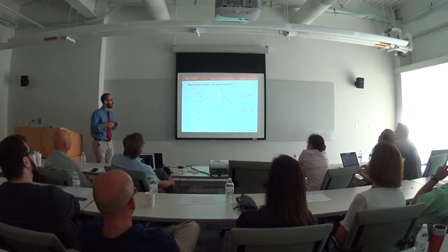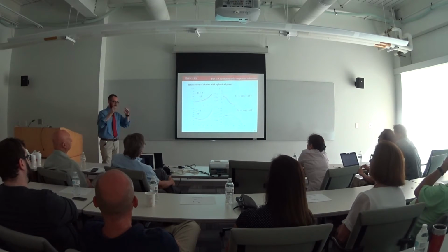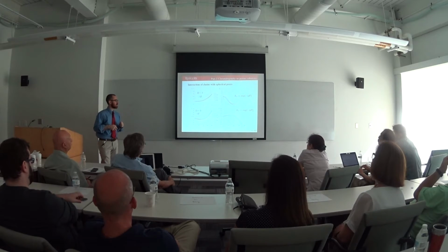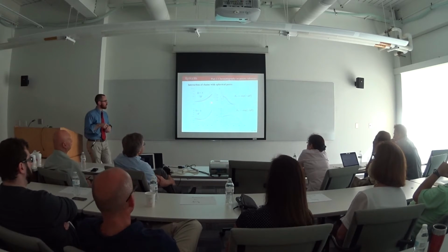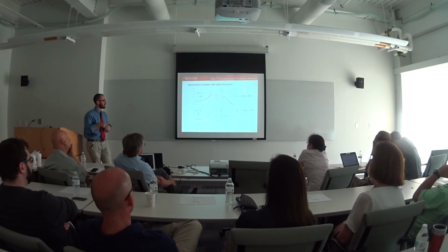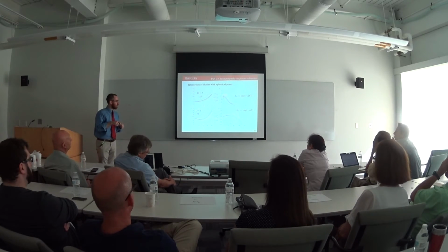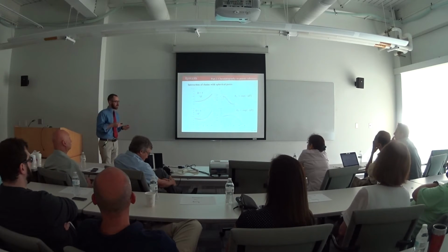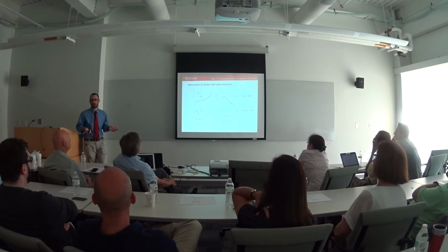This can also be shown by the partition coefficient of chains between free space and confined pores, which is just the difference in the free energy of those two chain types. So what we see in both, this is the partition coefficient of chains confined to a pore which is 3 beads wide, and this is one which is 8 beads wide. And so what we see is that at no point is the partition coefficient constant. So this would seem to completely kill the case of having critical conditions on porous materials.